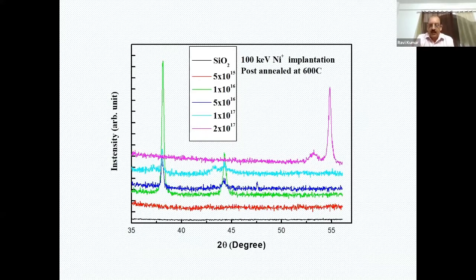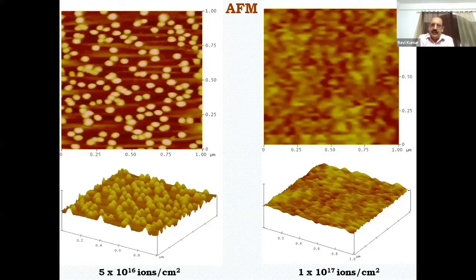First, we want to know their structure. You see the X-ray diffraction peaks, which clearly indicate nickel. They are indexed and matched with the pure metallic nickel structure, with the 111 peak and so on. Second, we did atomic force microscopy. Because it is very close to the surface, at 100 keV energy just below the surface, you can see the structure through atomic force microscopy, showing very nice spherical nanostructures of nickel metal present in the system.